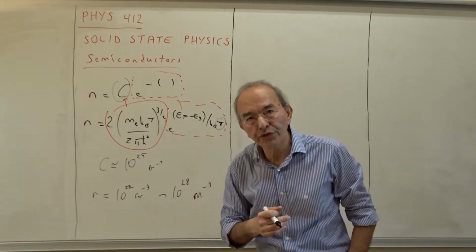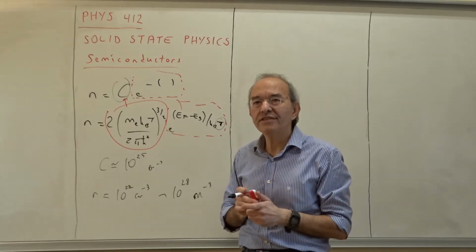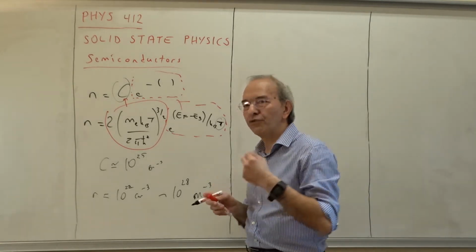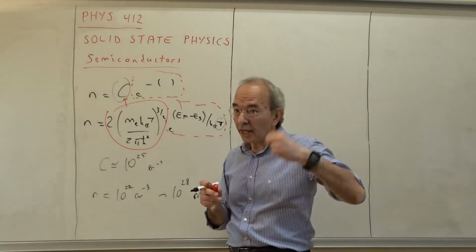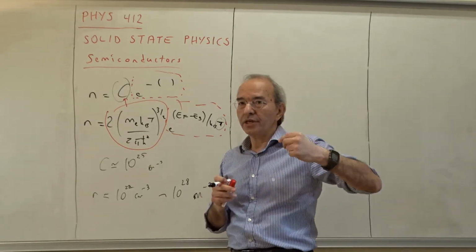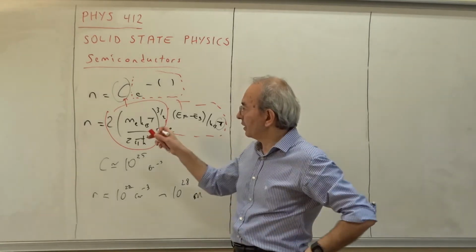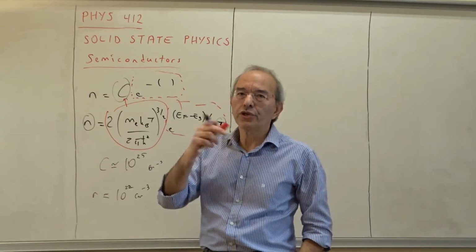And we have also learned that, unlike the case of metals, whose resistivities increase as a function of temperature, for the semiconductors this is just the opposite behavior. So the larger the temperature, the larger the conductivity as a result, because it means the larger the concentration of free electrons or free holes.